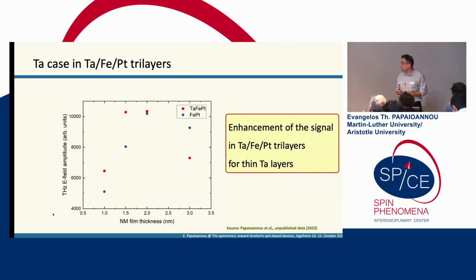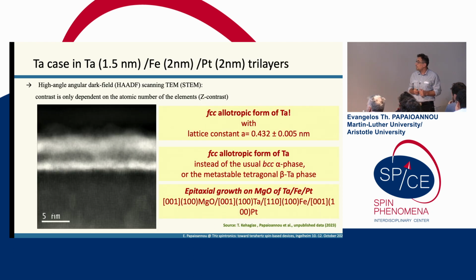So the enhancement, as I said, is for very thin tantalum thickness. And then we said, okay, what can happen? And I will show you now maybe a reason. So we went and performed structural analysis of our samples. And I present you the best sample, the 1.5, 2 nanometers tri-layer.